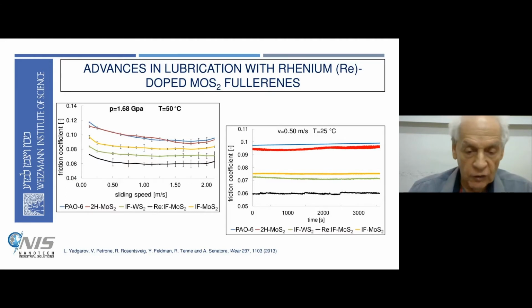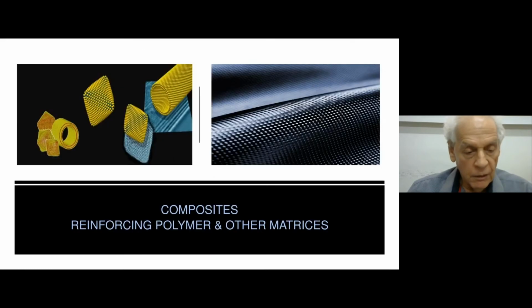This is another demonstration that if you use rhenium doping of our nanoparticles in a very precise way—and it's an extremely difficult experiment to put rhenium in the measured amount into these hollow nanoparticles—we get friction so low under very high pressure of 1.68 gigapascal, which is barely found in reality. Yet we can reduce friction from lubricants used today by a factor of at least 2 or 3, as you see from here to here. This is true for many kinds of experiments we did.